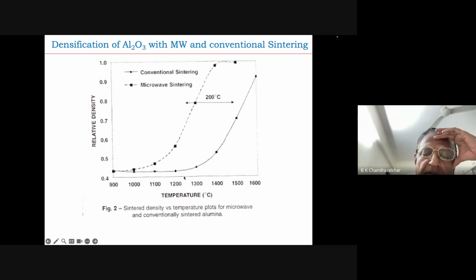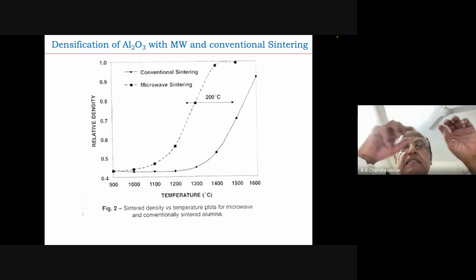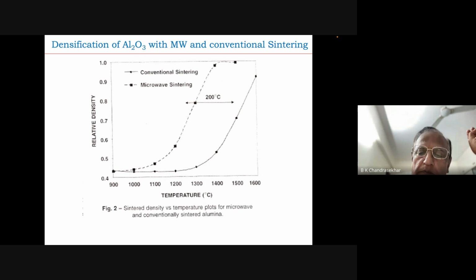But when you do it with microwave, you get much higher density very quickly, because it starts sintering very quickly. You are able to heat the sample very quickly, and the samples become very reactive even at much lower temperatures. So to get full theoretical density, you don't have to go up to 1600 degrees centigrade, you can reach it even at 1400 or 1450. There is a difference of about 150 to 200 degrees centigrade between conventional heating and microwave heating. First point is that the maximum temperature required is reduced.